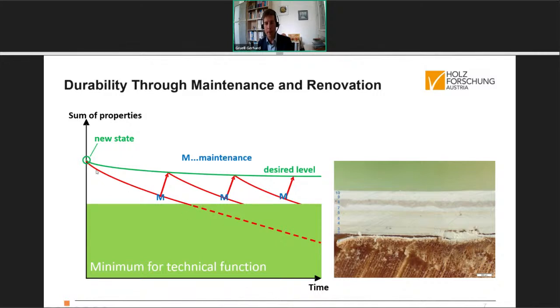And if we are above this minimum level, there is still some technical function of the coating, and maintenance should work out here. If we now make maintenance, we shift this curve up to a higher level, and then degradation goes again down here. We make some other maintenance and some more maintenance, and we come up here, but we never come underneath a minimum level for the technical function of the coating.